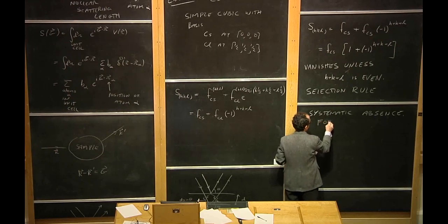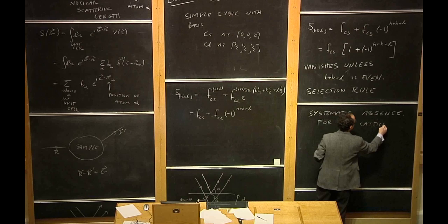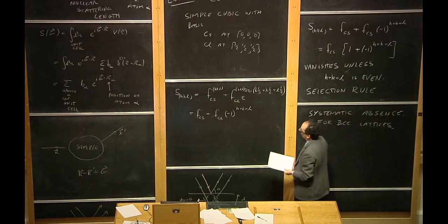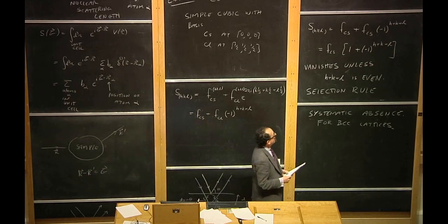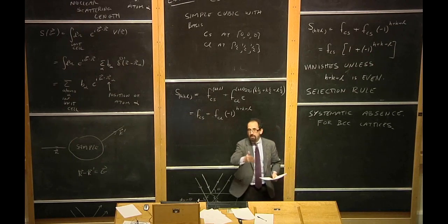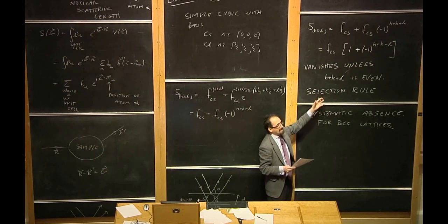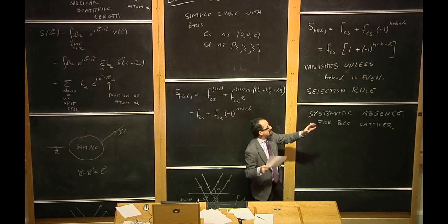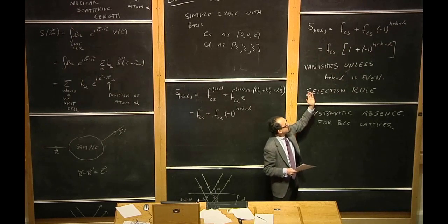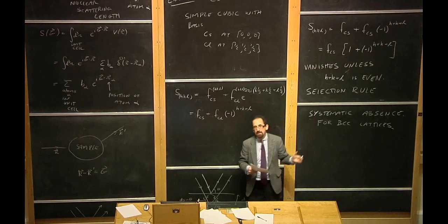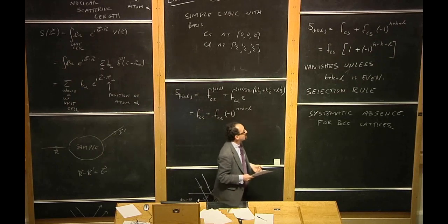These are the selection rules. Now, whenever you do a scattering experiment, if you discover that for all the Miller indices scattering by these wave vectors with h plus k plus l odd, there's no scattering at those Miller indices, but you do find scattering for h plus k plus l even, it's a very, very good bet that what you have is a BCC lattice.